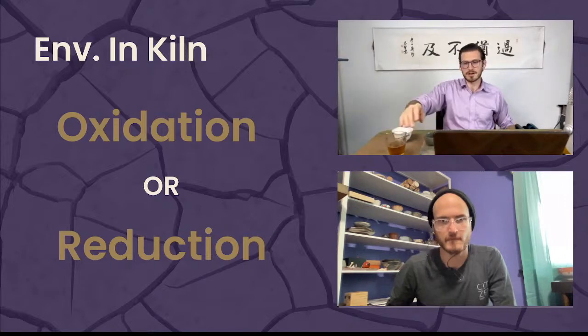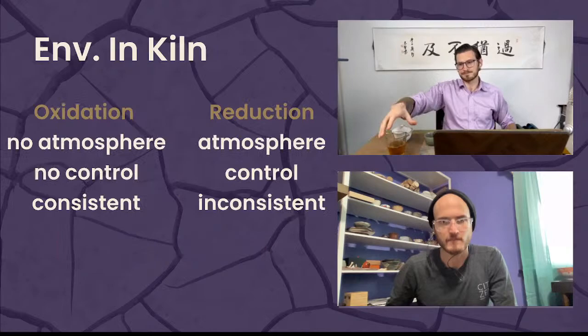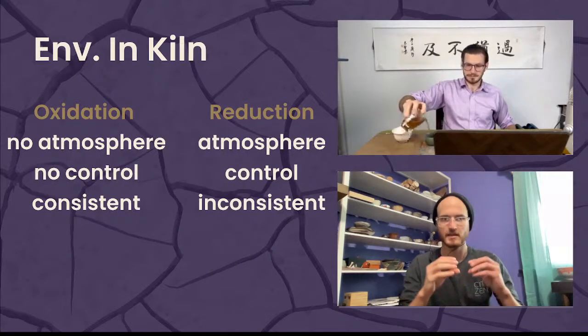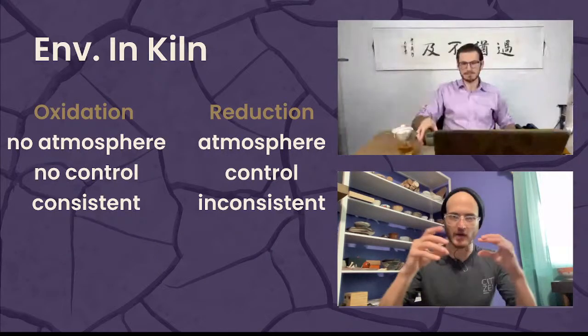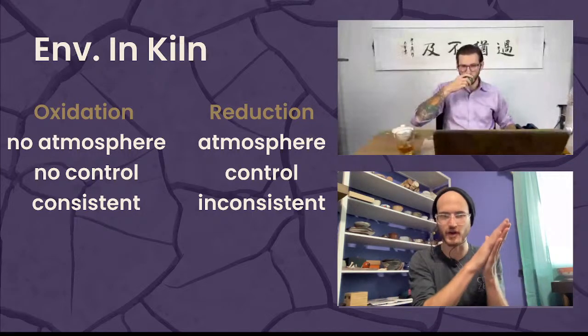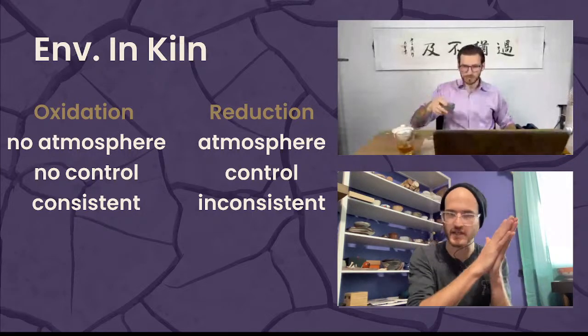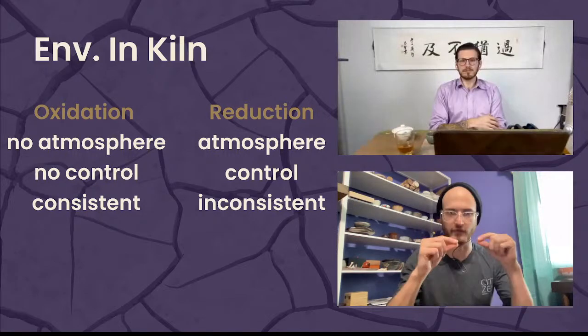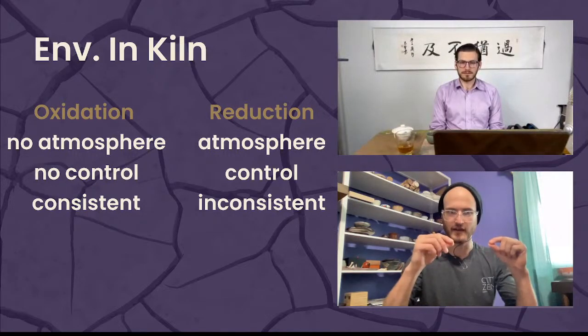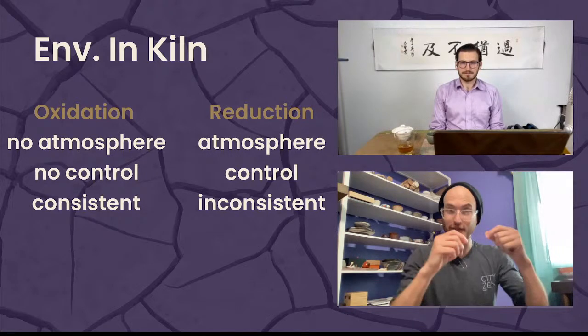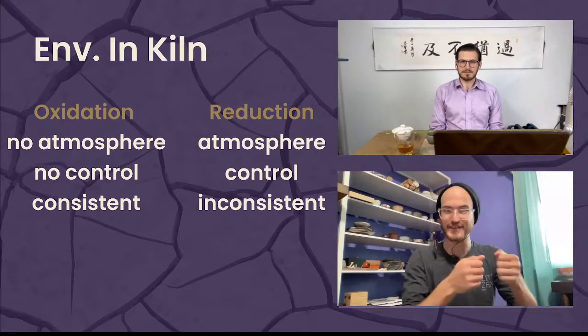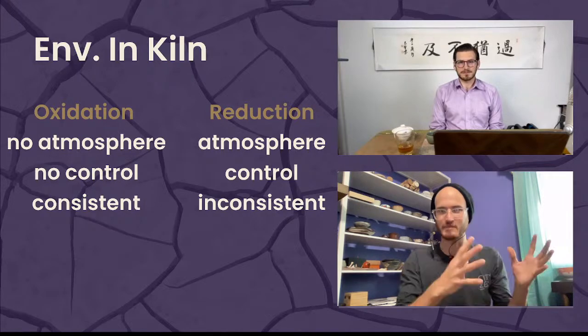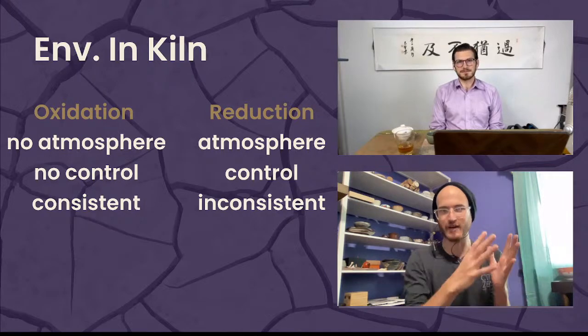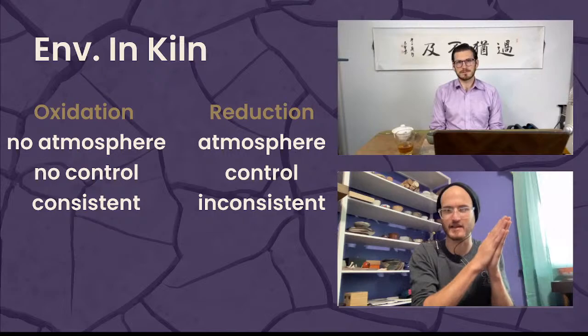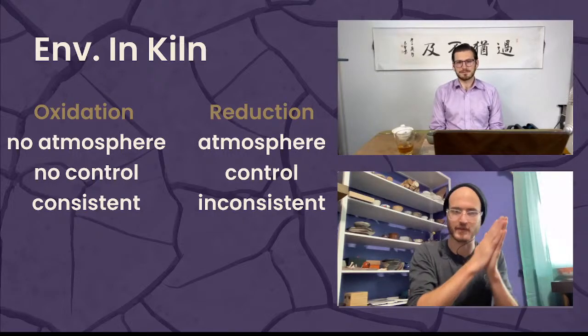Yeah, absolutely. So it's like the difference between if you took a sponge and you have all of these air pockets and an open structure, and then you squished it down into the tiny little bricks that you get from the grocery store where they're dehydrated and flat, right? That's a really strong little material, and it's kind of hard to work with or bend or do anything with. But then you add water to it, and all of a sudden it expands, right? The action of the fire is essentially the removal of water and space inside of that clay matrix, where it melts everything and compacts everything together.